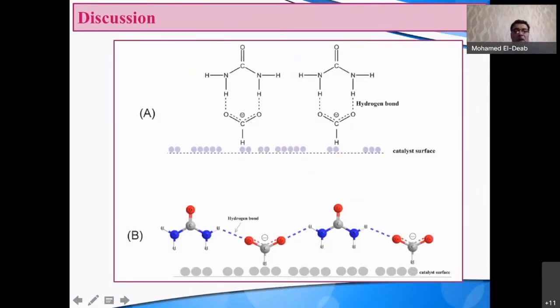We proposed some model. Actually here we proposed that urea acts as an antenna for formic acid, forming something like, as you see here, an 8-membered ring atop the surface of the catalyst layer, which orients the CH bond down to the catalyst layer. So the scissoring of the CH bond is visible and easy, so we can have CO2 directly from formic acid oxidation.